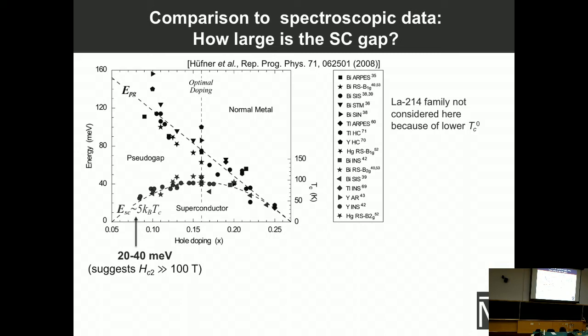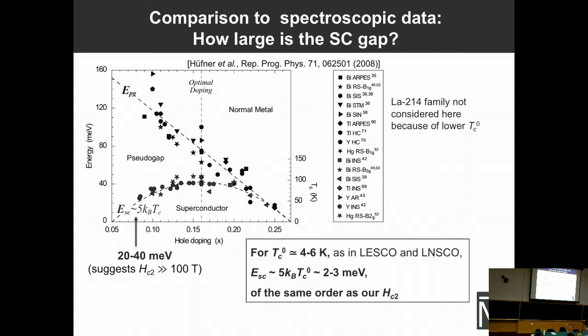Now, if we use the same expression and plug in our low values of TC, this would give a much smaller energy scale, which is of the same order as our upper critical field. And this agreement is, I think, striking, because in these comparisons, they were not even considering the lanthanum-based cuprates because they have much lower TCs. And they didn't want to make any normalization, so they were just looking at the absolute values.